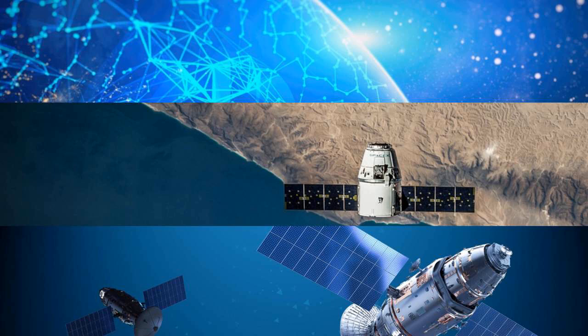It's extremely thin. It's in the range of about a micron, which is tailorable. Fully inorganic like all Acktar coatings. It has excellent adhesion to all kinds of substrates, extremely low outgassing, cleanable with traditional solvents, and qualified for thermal vacuum cycling, resistant to humidity and abrasion, and also thermally stable between minus 70 to 250 degrees Celsius. So it's a robust space-qualified thermal coating.